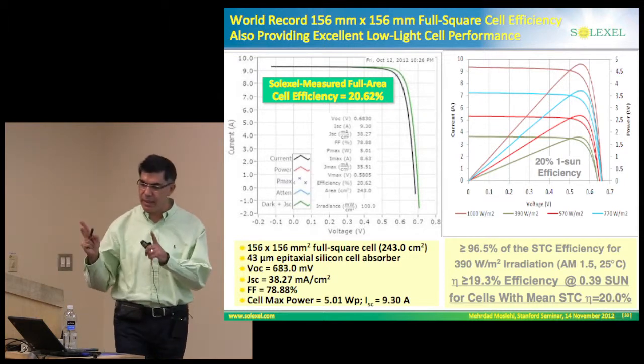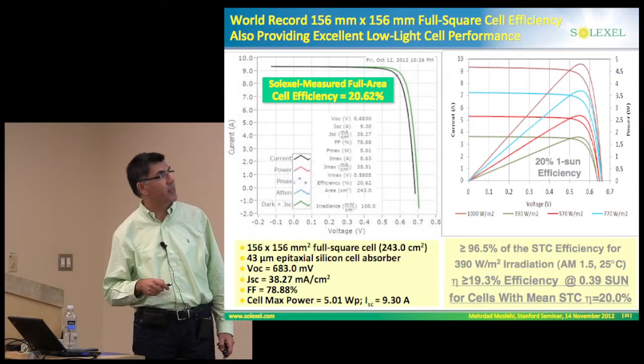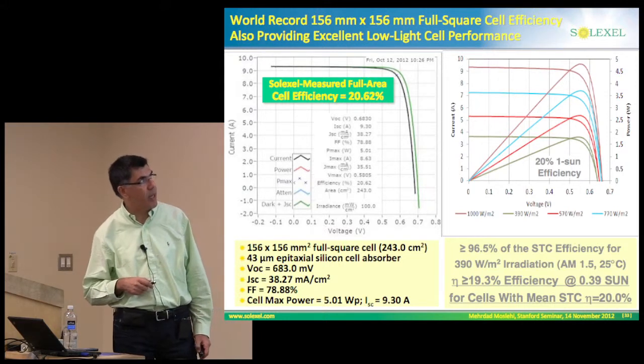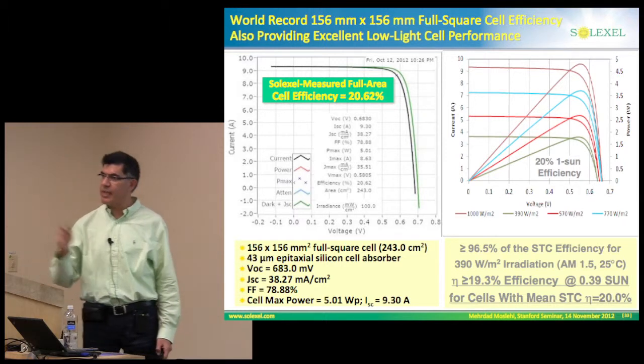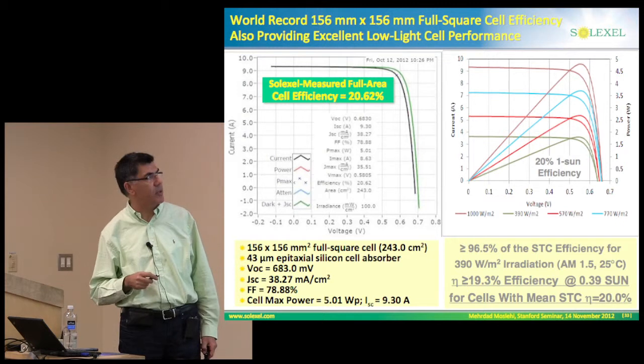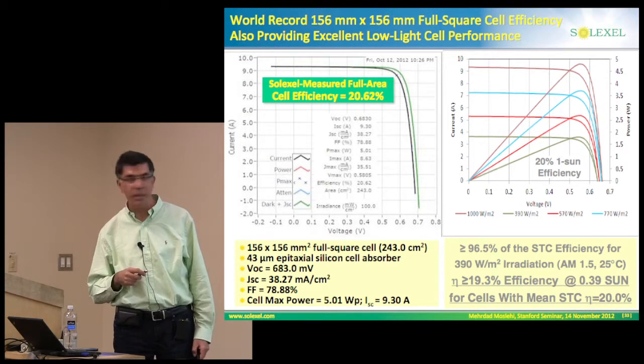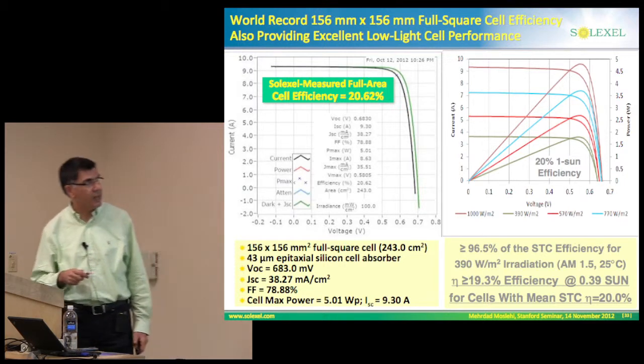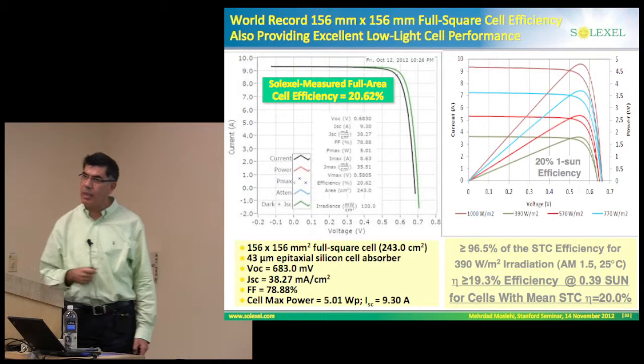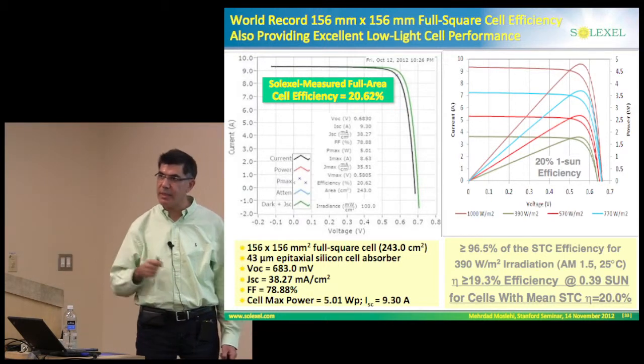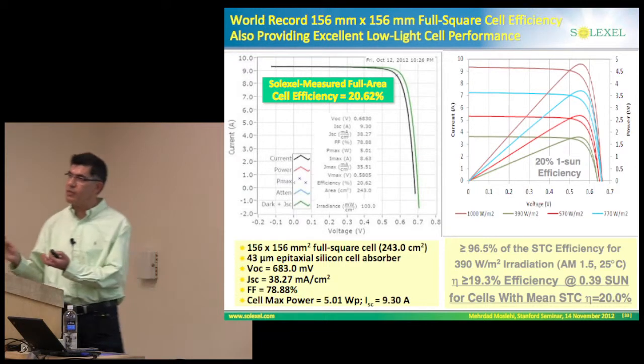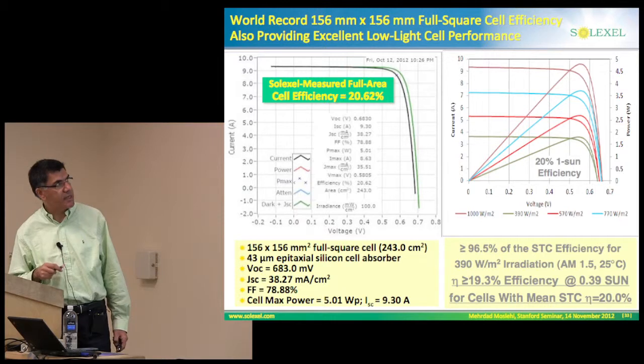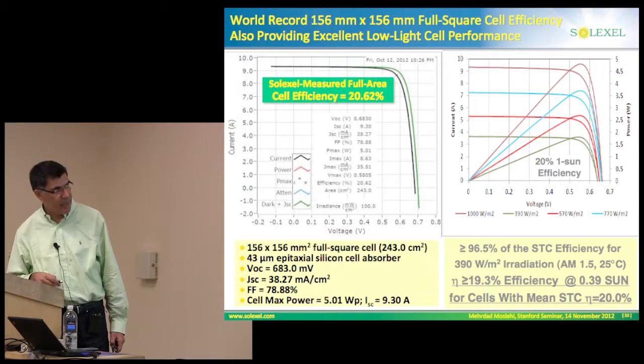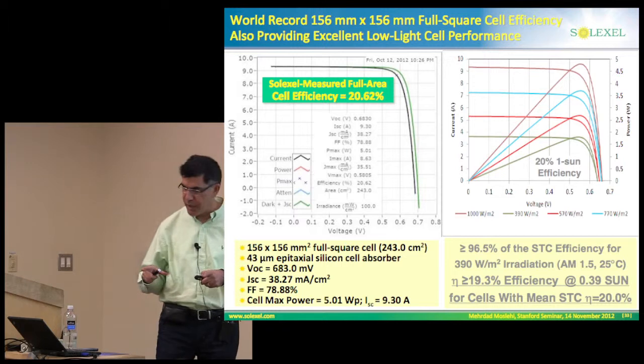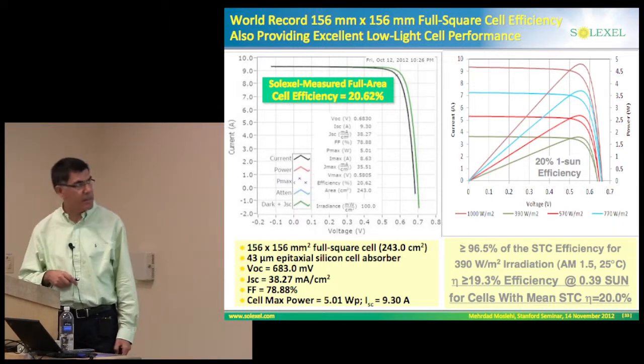So actually, shortly after we had submitted that for NREL measurement, we went to a higher champion. Typically, our cross-calibration with NREL is a couple of tenths of a percentage absolute. So we haven't yet done a new NREL certification. We see a very short-term roadmap with our technology to 22% cell efficiency. For us, that would enable module efficiency of 20%. For this cell, really, you see that the cell power is 5 watts, again, a record wattage for thin silicon cells.